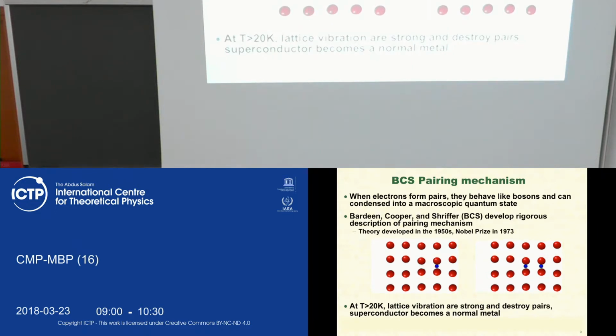Now let's get back to the pairing mechanism. And I really like this cartoon. What happens is that an electron propagating through the crystal actually interacts with the lattice vibrations, which are the phonons. And the pair which propagates along the crystal and talks to the lattice vibrations has all chances to be paired. So the lattice vibration provides a pairing mechanism, and also quite intuitively, if we increase temperature, we increase the lattice vibration, and it leads to destruction of the pair. This is how phonons influence and mediate superconductivity, providing a mechanism, and as I already mentioned, the theory of Bardeen-Cooper-Schrieffer was developed in 1957. The paper was published in 1957, and they got a Nobel Prize in 1972.